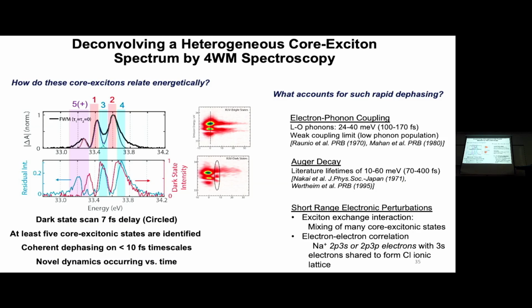And we've spent a lot of time thinking about the mechanisms of what plays a role in the decay, and we think the electron-phonon coupling, there's a specific mechanism that a phonon is launched when you create the core level exciton, is still the dominant way that these relax. And you see the relaxation is very, very fast, like sometimes a few femtoseconds. And so this has taught us a lot about core level excitons in solids that we never thought we could do and understand through the dynamics.